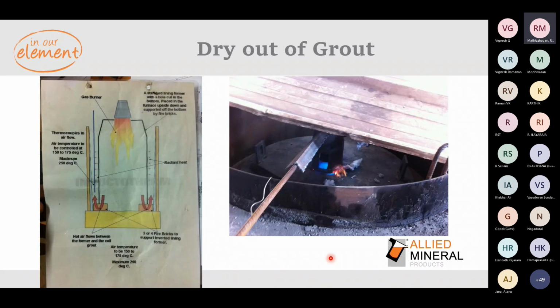So this slide talks about the dry out of a grout through a burner system. As you see in the slide, place the former upside down by placing a brick at the bottom. So the former will be standing over the bricks. Place the burner in such a way that the flame is inside the former and the hot air flows through the bottom and moves upward between the grout and the form. Place a thermocouple through which you can detect the temperature and we can control the temperature.